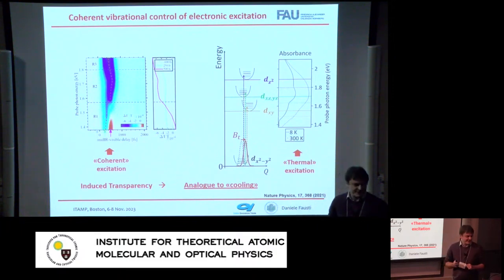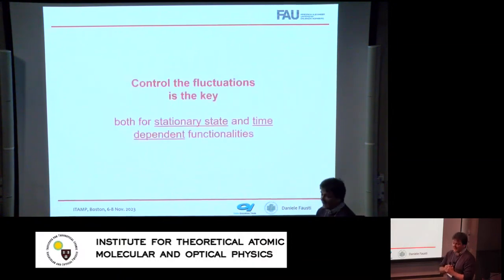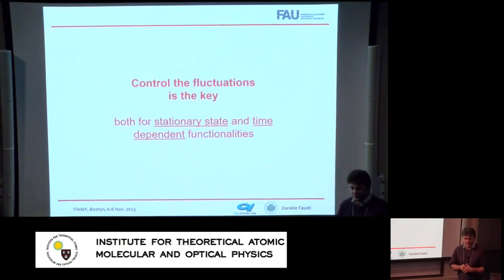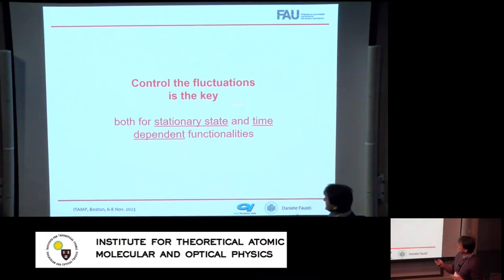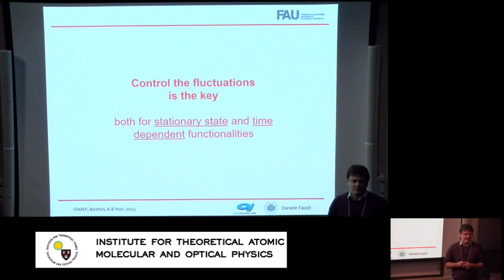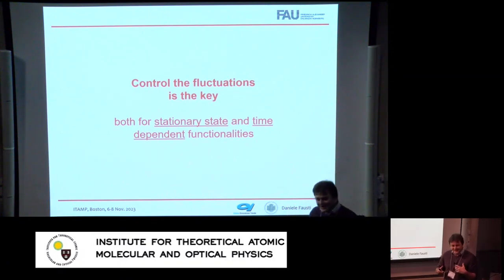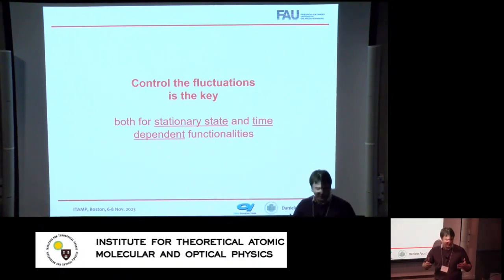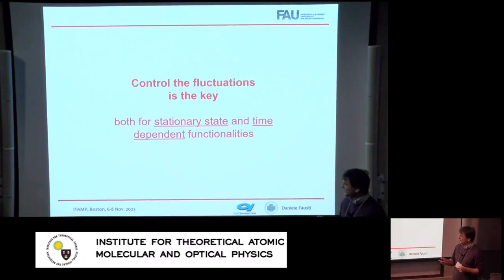But the general message of these slides is that whenever I want to do something which goes against thermodynamics, there is a quantity which I think is crucial, and it came out in different talks, and it's the fluctuations in the system. So rather than driving the system, I should try to dynamically control the fluctuations. And we've seen, for instance, also in the cosmonic thing that was mentioned in the morning, that the interesting effects come from the fact that I can induce a non-trivial fluctuation structure, a time-dependent fluctuation structure.